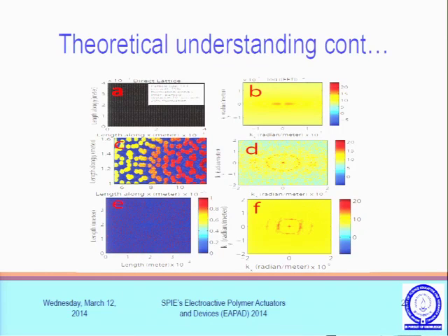So this is the theory. We have used many kinds of noise. We have put noise in shape, size, and orientation, and we have found various diffraction patterns. But the last one is very close to our experimental finding. It means that shape, size, and orientational disorder in the structural arrangement play a crucial role.